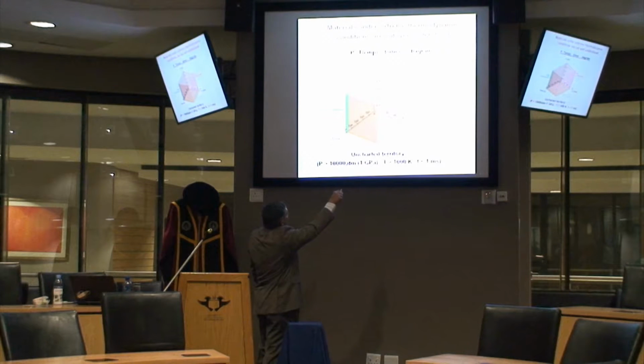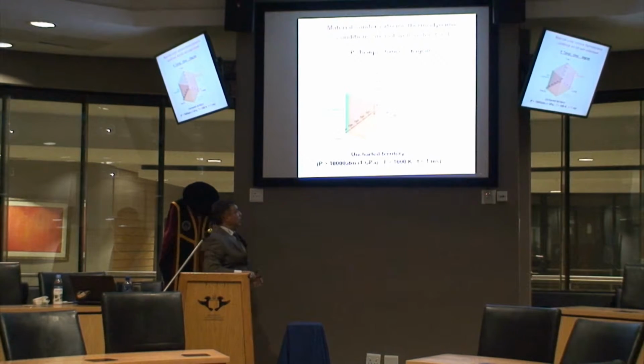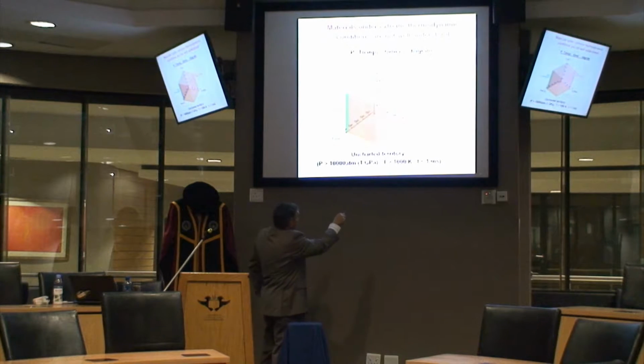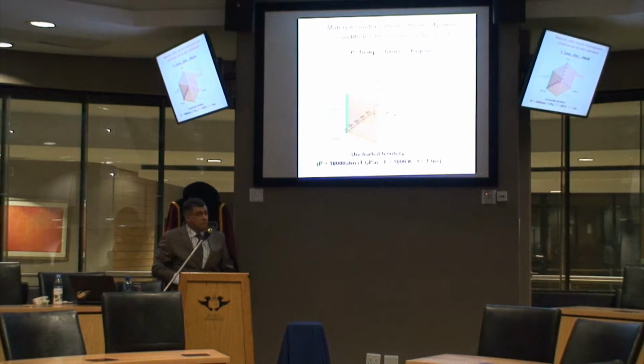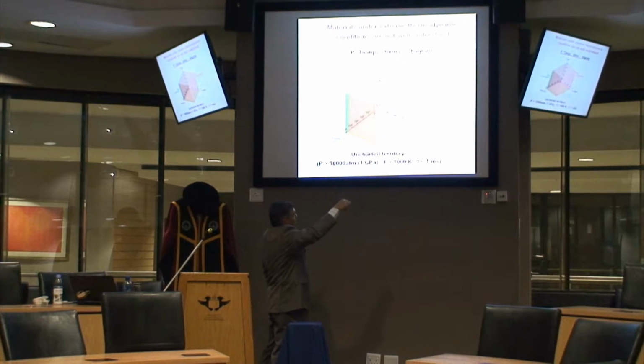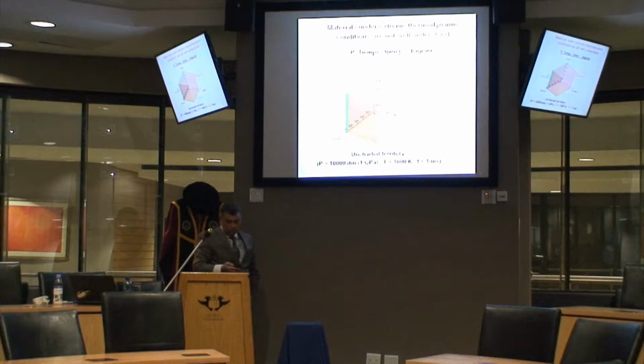On this slide, I've plotted temperature on this axis in funny units, time on this axis, and pressure on this axis. Room temperature is down here somewhere. If I change the temperature of the material and wait a certain amount of time and investigate it, we understand fairly well what is going on. If I stay at room temperature, that's this plane. If I stay at room temperature and change the pressure, that's on this plane, it's somewhat well understood. If I vary the temperature to high temperatures and the pressure, that is very poorly understood and largely unexplored. And the same applies to decreasing the pressure, the plane at the bottom. Just to emphasize the importance of concurrent extreme PT.